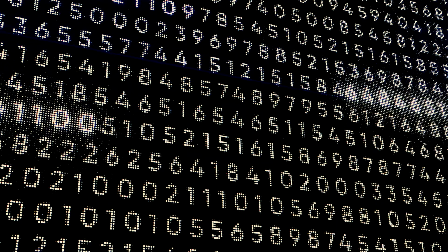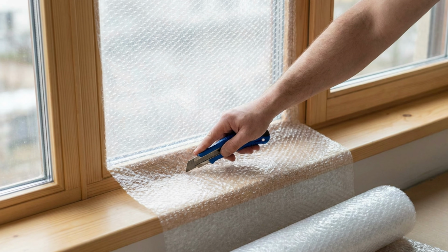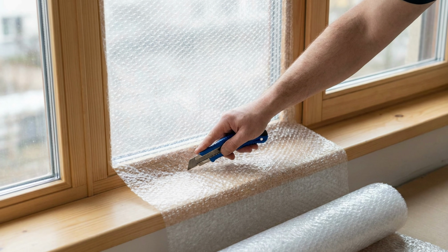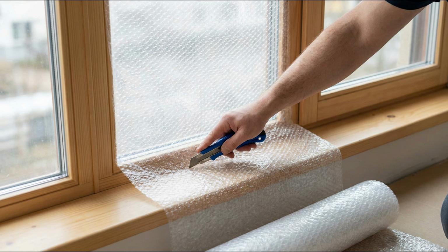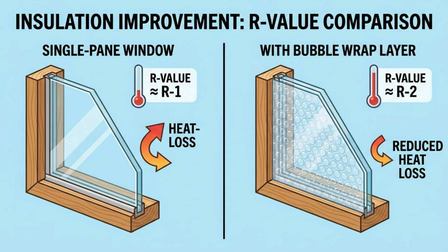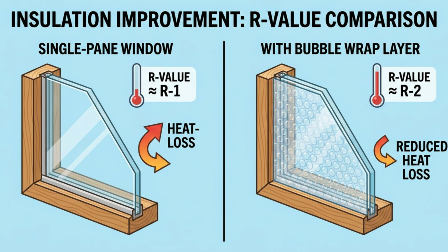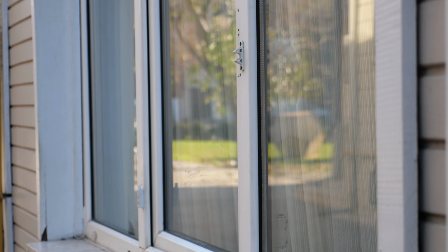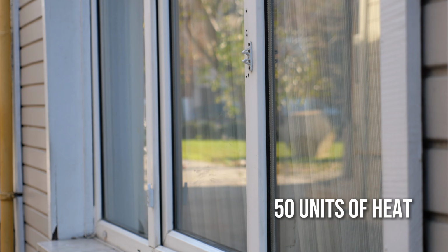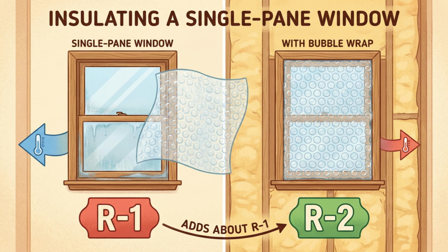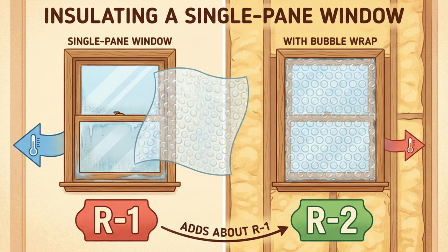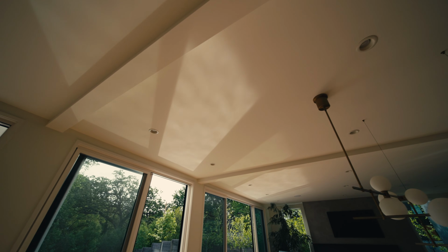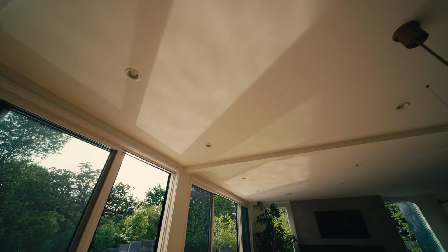The numbers back it up, and they're not subtle. A guy named Gary, who runs Build It Solar, an engineer who actually puts instruments on this stuff instead of guessing, measured it directly. A single pane window sits around R1. Add a layer of bubble wrap, and it climbs to about R2. You doubled the insulation value of the glass. And doubling it means that instead of losing 100 units of heat through that window on a cold night, you lose about 50. That's the whole claim. That's where cuts it in half comes from. The heat pouring out of your worst windows. Cut by half for the price of a sheet you were going to throw away. That number stopped me the first time I read it, because nothing that costs $0 is supposed to do half the work of a several $100 window.